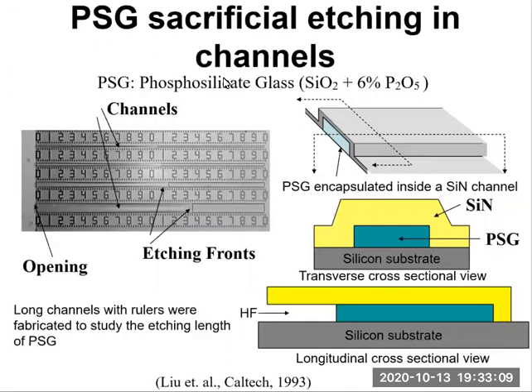To study PSG sacrificial etching, PSG is arranged as shown in this figure. PSG is encapsulated inside silicon nitride channels. So this channel wall is made of silicon nitride. We know that this is a low stress silicon-rich silicon nitride, because stoichiometric silicon nitride has a very large stress, and we typically do not use stoichiometric silicon nitride.